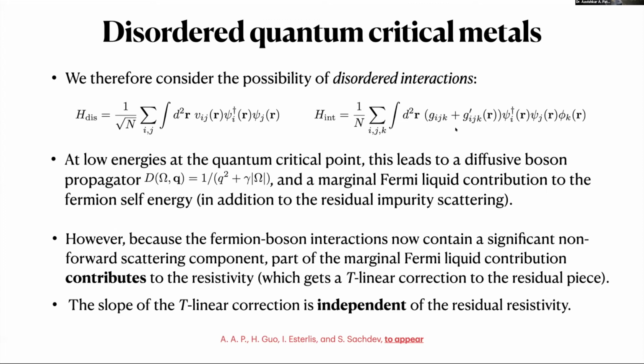Now, again, when you do this, you end up with a boson propagator that's the same form and a marginal Fermi liquid fermion self-energy. But now there is an interaction between the fermions and the bosons that because it's spatially random, it's no longer forward scattering. It can scatter by large amounts of momentum because it breaks translational invariance. And that relaxes both current and momentum and gives you a T-linear contribution to the resistivity. So resistivity is now constant plus T-linear, and the slope of the T-linear correction derives from a different parameter, G prime, whereas the intercept, the residual resistivity, derives from this parameter V. So there are two independent parameters.